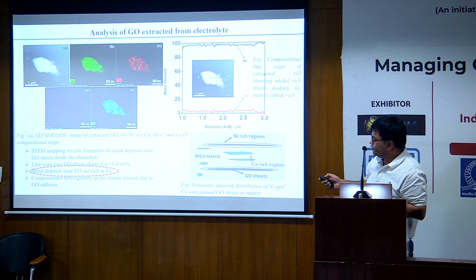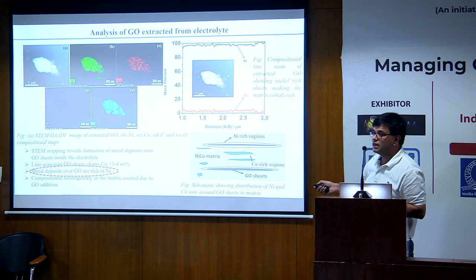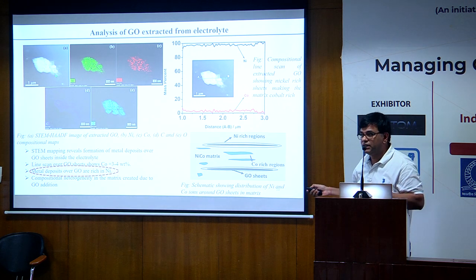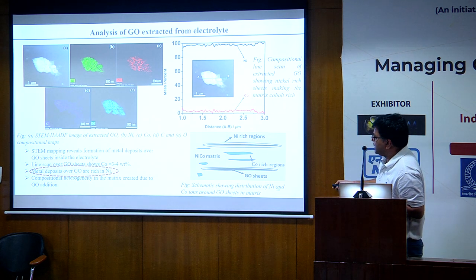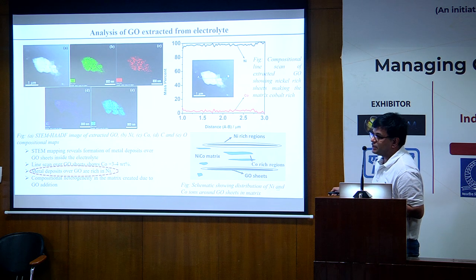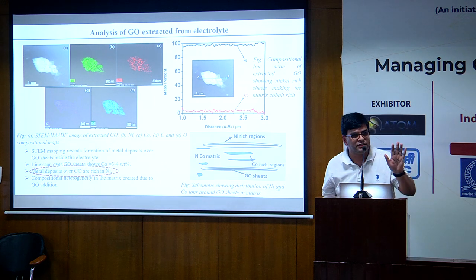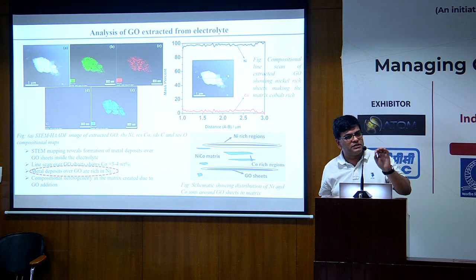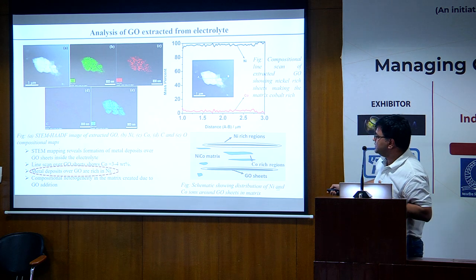It is in the electrolyte, and before it even gets into the coating, it is very highly coated with nickel. That means that if you take a coating like this, a schematic, and this is the graphene oxide region, then that region is nickel rich. And that simply means that the regions in between the graphene oxide sheets must be cobalt rich, because the nominal composition, the average composition, is fixed. So if this region is nickel rich, then this region has to be cobalt rich.